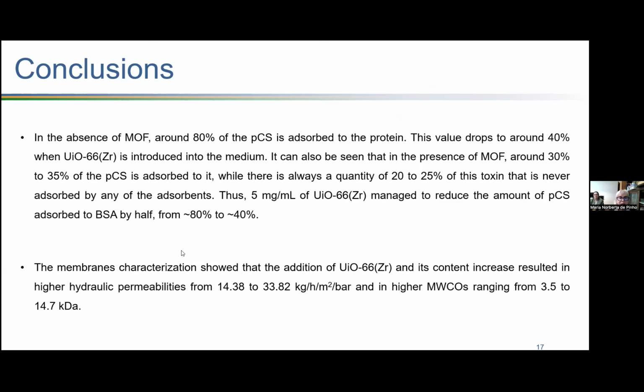Okay, so in conclusion, in fact, we have a MOF that brings down the p-cresyl adsorbed to the protein from 80% to 40%. And the membranes showed that the addition of MOF and the increase of its content gives higher hydraulic permeabilities, ranging from 14 to 34 kilograms per hour per square meter per bar, and higher molecular weight cutoffs are brought by the inclusion of the MOF.